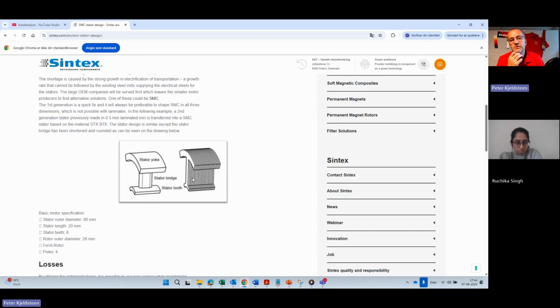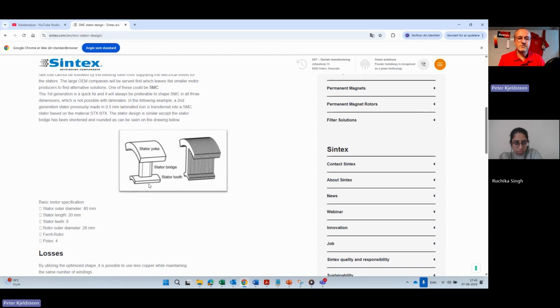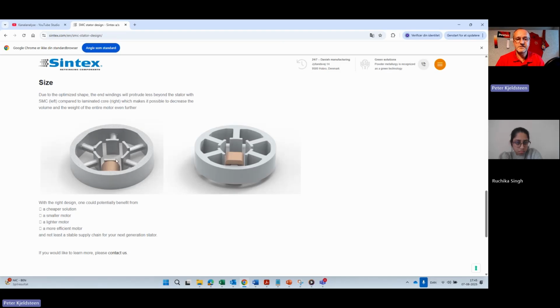When you're working with SMC, you are able to make different heights. When you make laminations, you have laminate by laminate, so you have uniform height all over the piece. But when working with powder, we can make the yoke high, we can make the bridge small, and we can make the tooth high. And that results in a motor that looks like this. Meaning that when you have standard height with laminations, you have your end winding. The winding goes above the height of the stator. But if you can reduce it, you can put the winding inside the height of the yoke. This means that your winding is shorter.